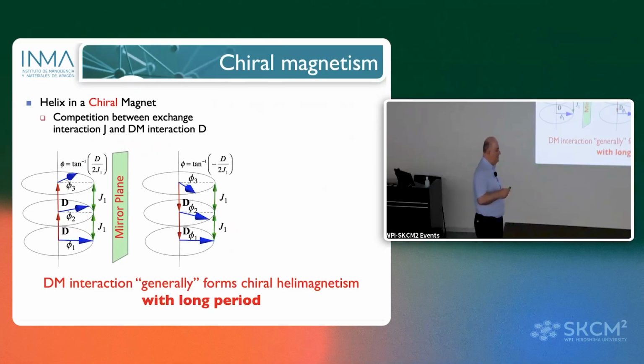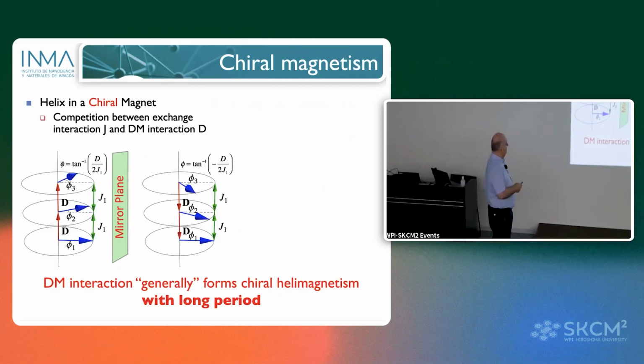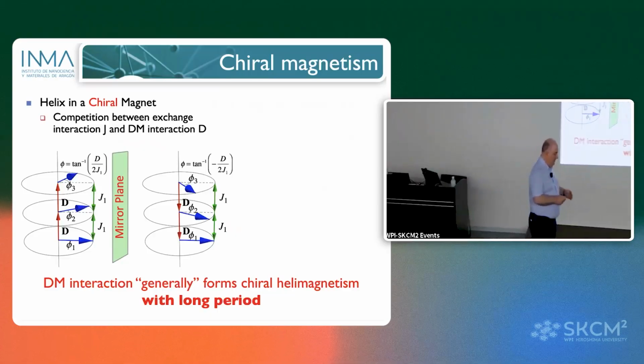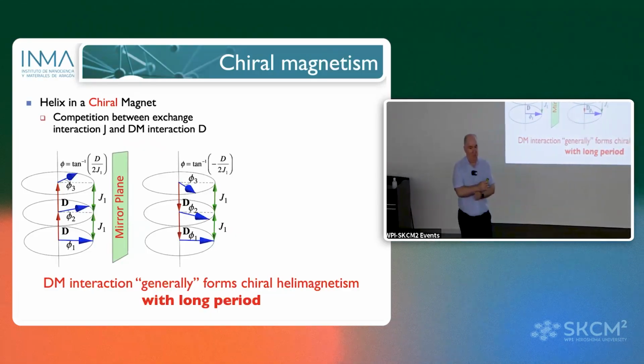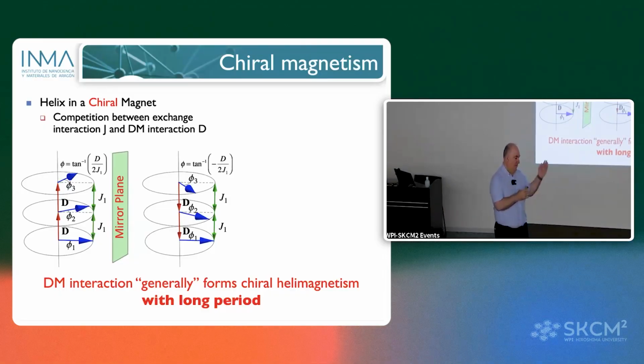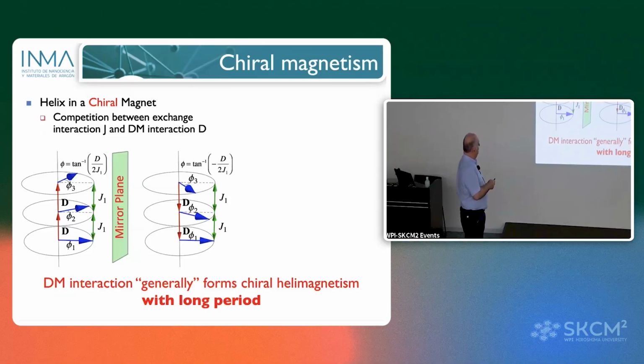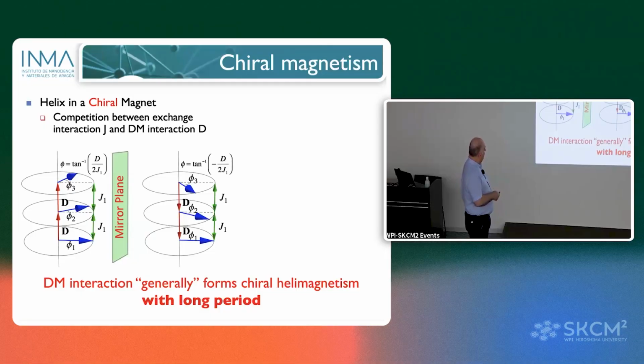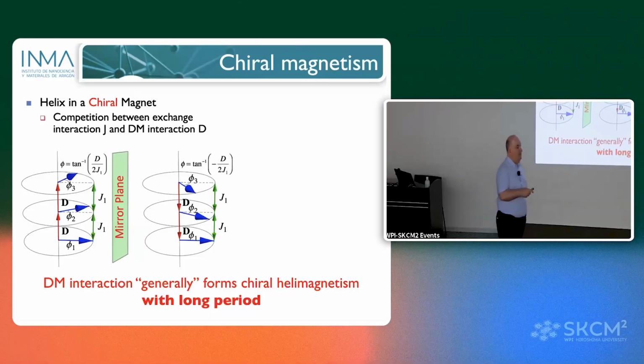Important. We can have helices originated by the Dzyaloshinskii-Moriya interaction, in which you have a kind of competition between an interaction, the Dzyaloshinskii-Moriya, that wants to order the spins or the magnetic moments 90 degrees, and the exchange interactions that want to order parallel or anti-parallel the spins. Then the competition of both will produce this kind of helices in which the pitch angle is related with the ratio between the Dzyaloshinskii-Moriya and exchange interaction. In this case, one enantiomer is transformed in the other one, for example, by mirror plane, and one enantiomer has different energy than the other.